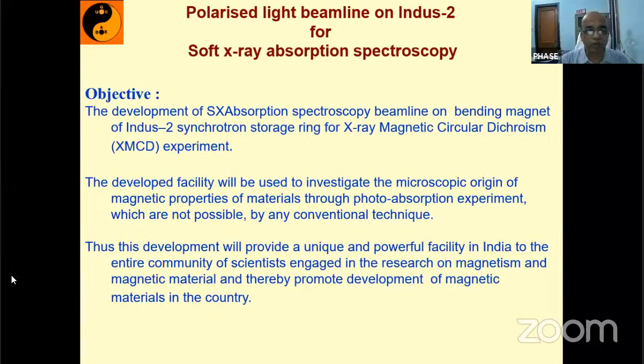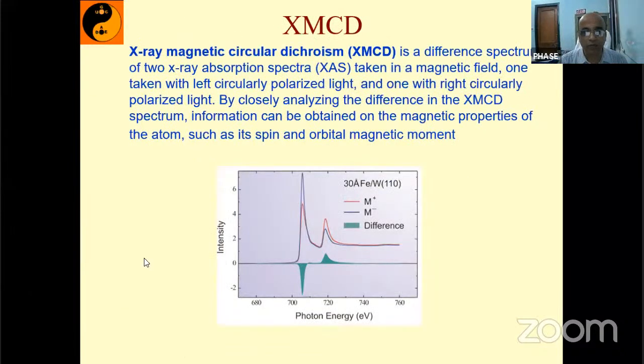And then I will tell you about the polarization property we have used to develop the technique for magnetic measurement. The polarizer, you know, above and below: if you tap the beam, then one can get polarized light in the synchrotron radiation. So if you have the two types of polarized beam, one can do the absorption experiment using both polarizations, that is left circular polarization and right circular polarization. The same sample can be used for the two types of absorption experiment.